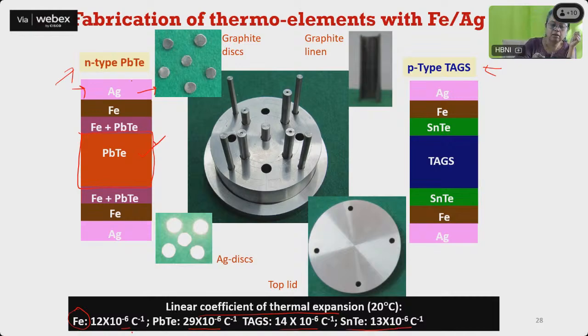We are not directly putting the silver pads on it. We are putting a layer of iron on the lead telluride. And in case of the TAGS, we are keeping a layer of tin telluride, then iron, and then silver, so that there is proper matching in the thermal expansion, so that the legs, our thermoelectric elements, the modules do not break, or this junction should not come out when we are operating it at a temperature like, we have a hot junction. This will be say at 500 degrees centigrade. I have a cold junction. This will be at 25 degrees centigrade.